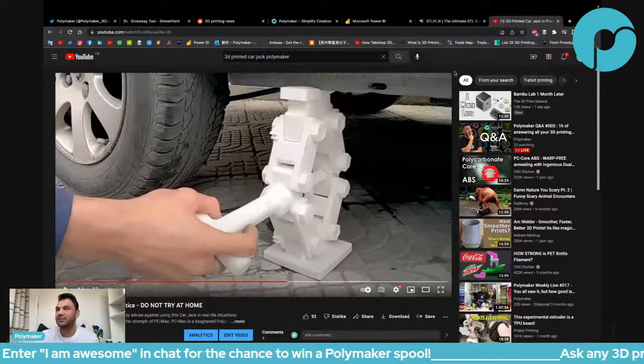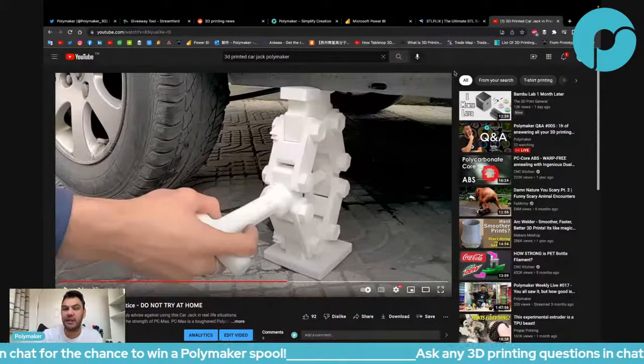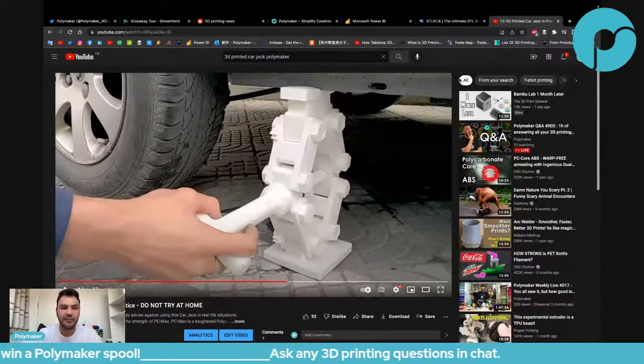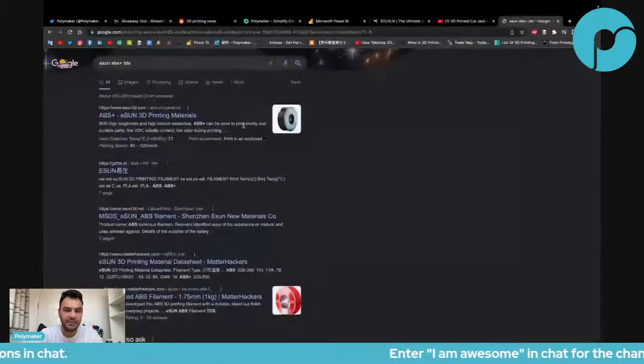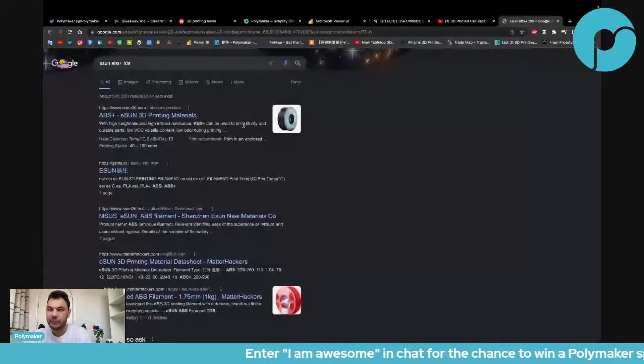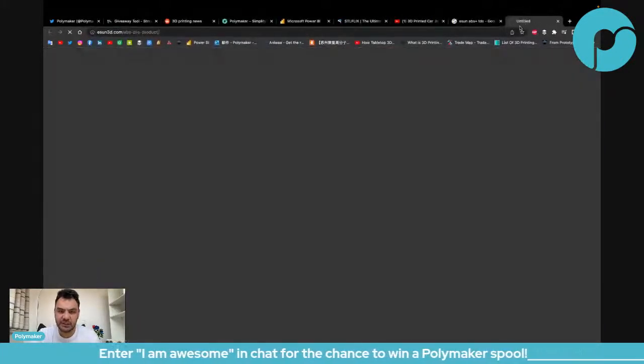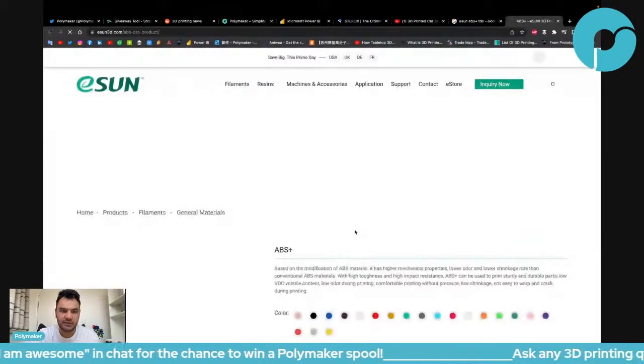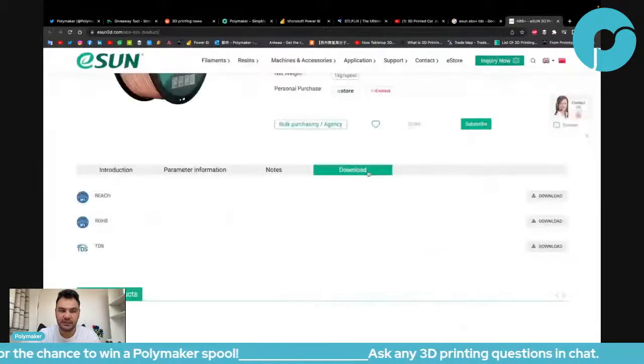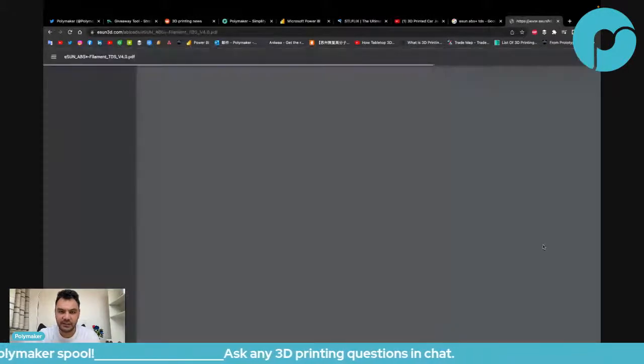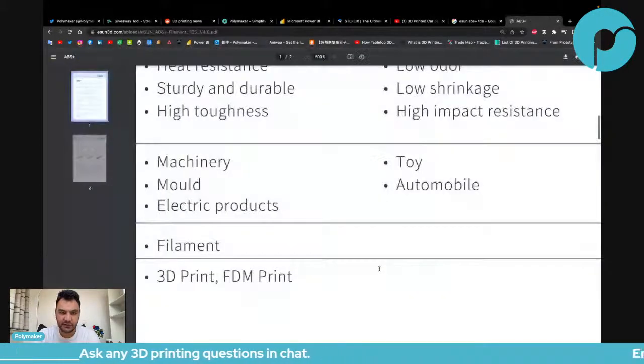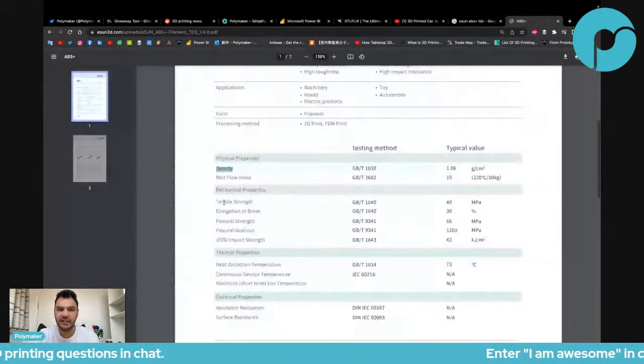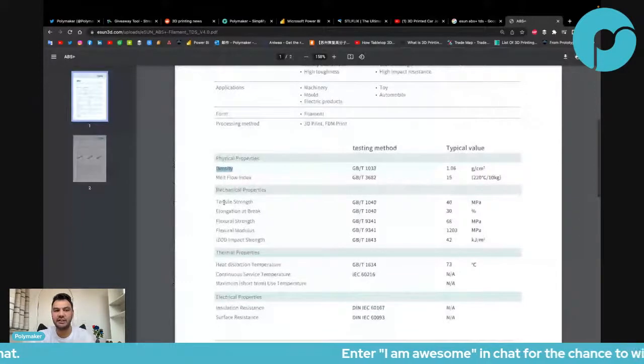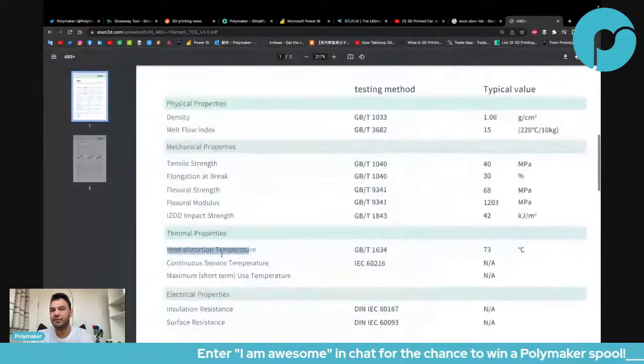Does that mean eSUN ABS+ will start softening at 73 degrees C? Yeah. I'm not sure if I can find back the TDS. Maybe I can, because I think it was sent from someone. Let me check. Maybe we can find it quickly. ABS Plus, download, TDS, and then the tensile, flexural, thermal properties. You see, so you have the HDT here, heat distortion temperature, and it's 73 degrees.